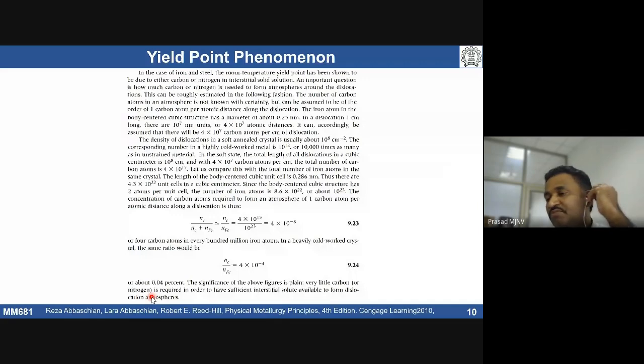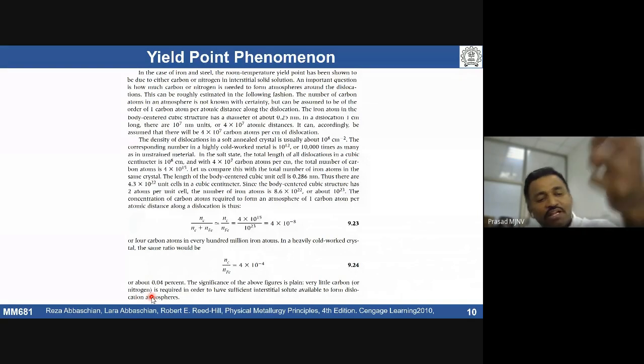That is the kind of thing that has to be avoided. How do we avoid it? What are the different methods available to avoid it? I have low carbon steel, for example, many of our sheets, refrigerator sheets, automotive car bodies. Most regular, conventional cars use low carbon steels, and these low carbon steels in annealed condition will be used for forming, easy forming, but the problem we are going to see is a yield point phenomenon. That can lead to a rough surface, so one has to avoid it. What kind of techniques should one use?